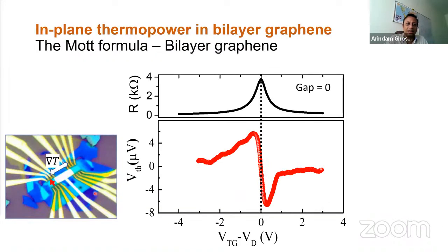So this is just an example of how this formula works. Resistance as a function of gate voltage, usually in a graphene-based system, shows this bell-shaped behavior. And you can see a typical device that we make in the laboratory. Here is a gated region, and by passing a heating current on one end of the sample, you create a temperature gradient across the sample in this direction. The corresponding voltage that generates is given by VTH, and you can see this red curve is the thermal voltage, which looks almost like a derivative of the resistance versus gate voltage or density.